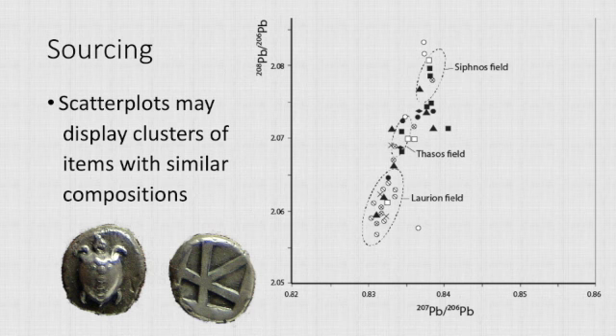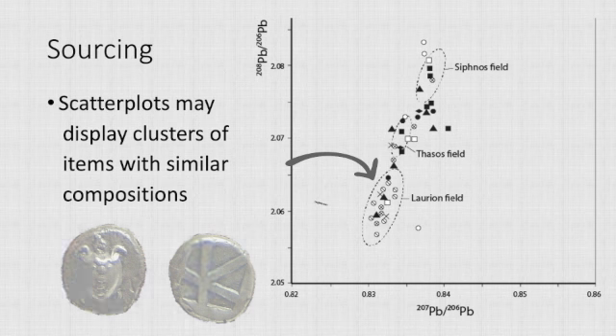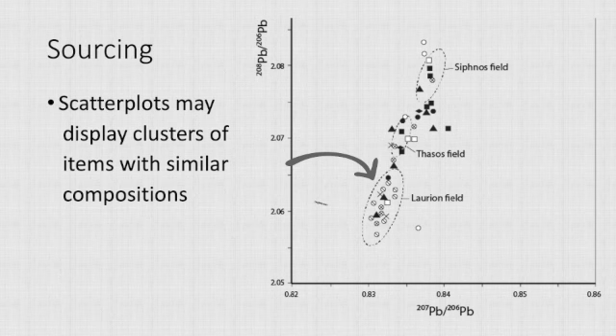When we measure the lead isotopes in silver of known sources, the lead from Sifnos separates out quite nicely on a scatter plot from the lead from Laurion, which was the silver mine closest to Athens. Leads from Thasos fall in between these two groups. When we also measure the lead isotopes in ancient Greek silver coins, we can match them up to these fields. Not surprisingly, most Athenian coins and some of the ones from Corinth fall within the Laurion group, and coins from Thasos fall within the Thasos group. But the city-state of Aegina seems to have used more than one source for its silver coins.